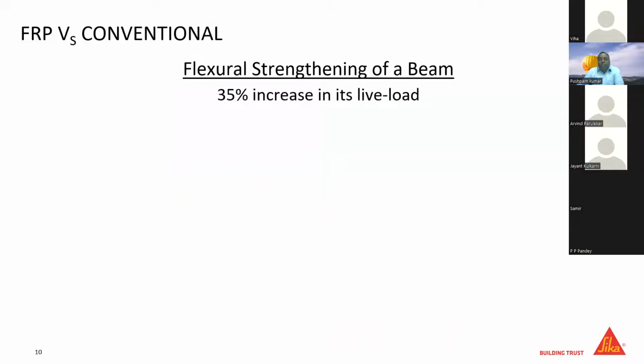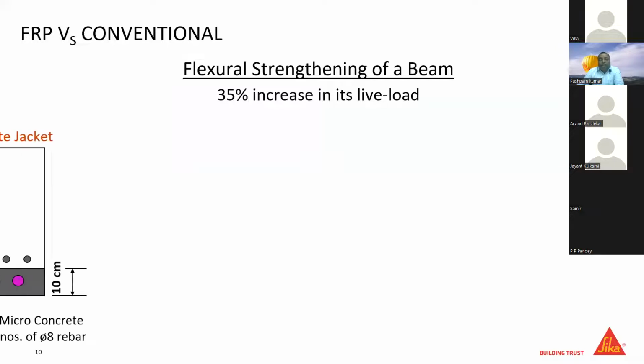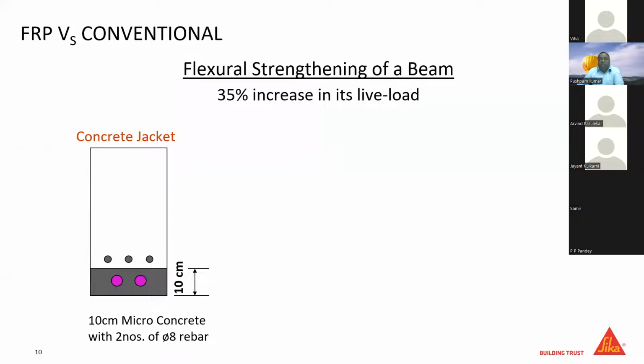I've just made a comparison between FRP versus conventional technique. You can see there was a case wherein a 35% increase in the live load was there on the beam member. For this, the conventional method of repair was jacketing with micro concrete with 100 millimeter thickness with additional reinforcement of 2 bars of 8 diameter, used for increasing 35% of live load.